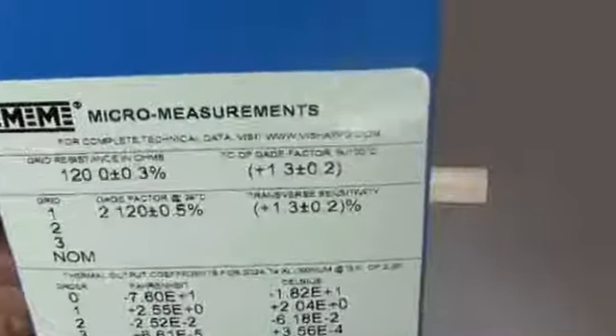So the first thing, we want to show you the gauge that we're going to be using. This is a Micro Measurements CEA series strain gauge. It is 13 self-temperature comp. We're going to be bonding this gauge to a sample of aluminum here. The pattern is a 125 UW, a very, very common strain gauge pattern. Gauge length is 1/8 of an inch, and the resistance is 120 ohms.